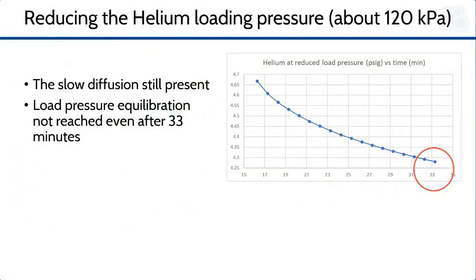The first trial to solve the issue of long equilibration time is to reduce the gas loading pressure in the sample chamber. The standard procedure consists in performing the experiment at room temperature and loading the gas at about 230 kPa absolute pressure. That might be the reason of the slow diffusion. We reduced the loading pressure to 120 kPa. This is a typical procedure when testing closed cell foams. Unfortunately, also at reduced pressure, we had an equilibration time of more than 30 minutes, and that is not acceptable for our task.